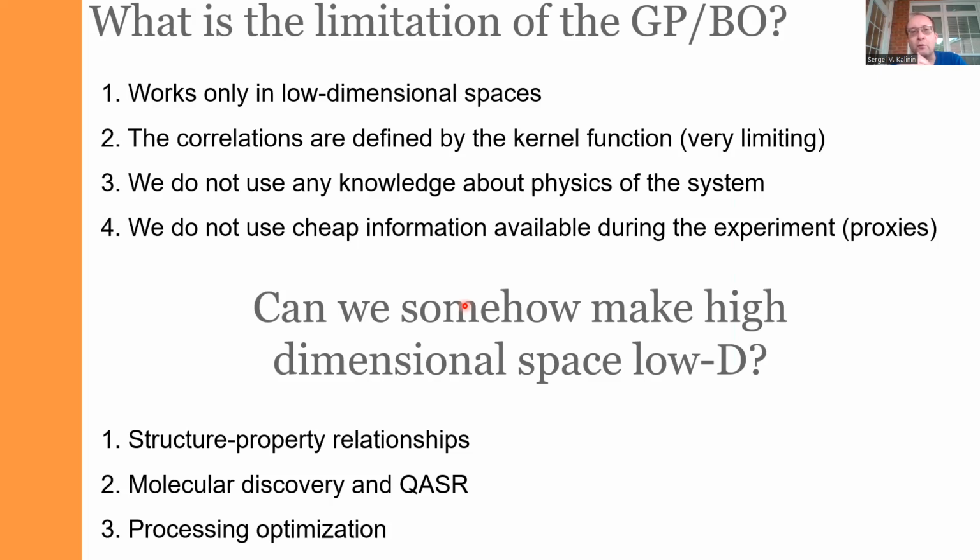So practically, if you want to use Bayesian optimization with Gaussian processes over a sufficiently complex space, even, let's say, two or three or four dimensional, and your function has multiple maxima and minima, you actually have to have a fairly considerable number of points. The purpose of the first notebooks was to illustrate how exactly that works. It gives you an idea that if you expect rapid changes in your behavior, your Gaussian process kernel length should be comparable to the length scale at which properties vary. So take it to the power of the dimensionality of the parameter space and you have an idea what your experimental budget should be. All domains are different, but in the cases I worked with, GP will give you a factor of three better than grid search or something like Sobol partitioning, but maybe no more than that.